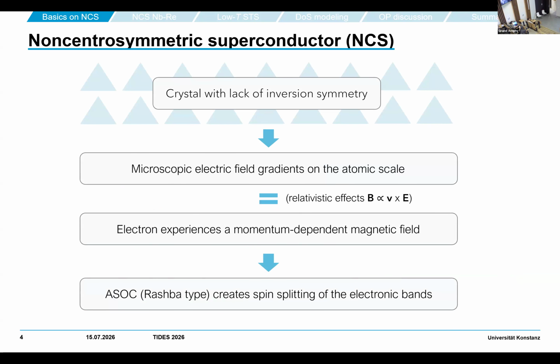If we have a crystal that lacks inversion symmetry, there are always internal electric fields which act on the atomic length scale, and they give rise to internal momentum-dependent magnetic fields. As a result, there will be Rashba-type antisymmetric spin-orbit coupling. Then it depends on how big this is and if it's a sizable effect.